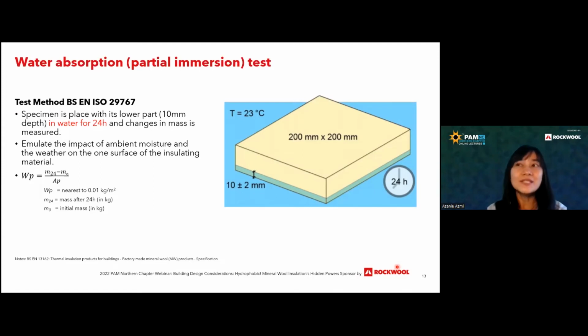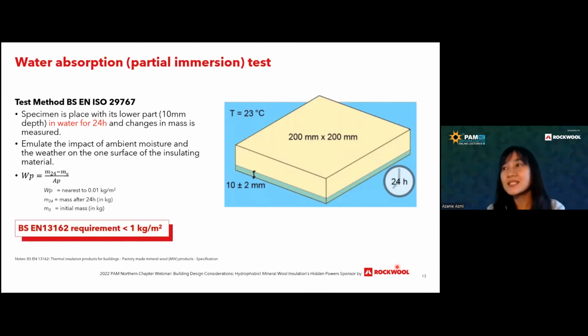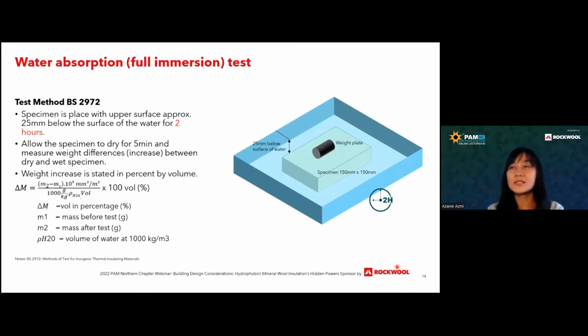And you will see that in the datasheet, what we declare is in kg per meter square. So how much is actually compliant? We look into EN 13162, which is the standard specification for thermal insulations, and usually the Europeans use these standards. It states that the partial immersion water should not be more than 1 kg per square meter. Okay, that is about partial.